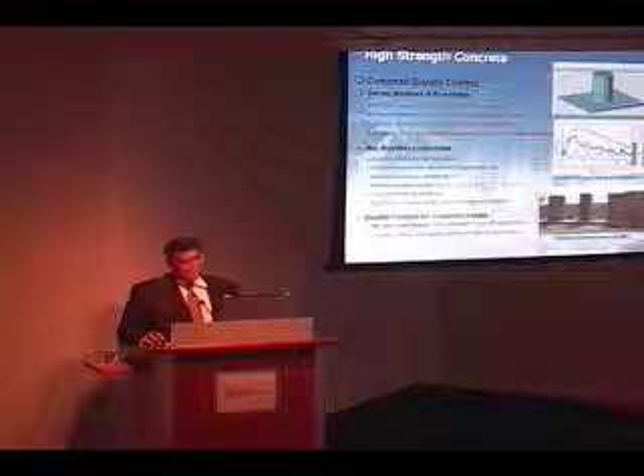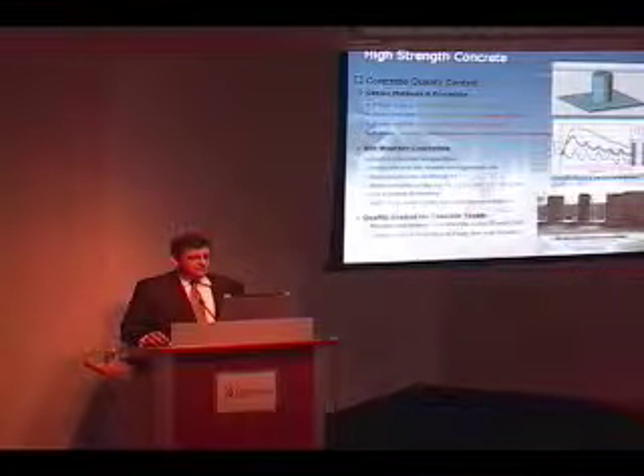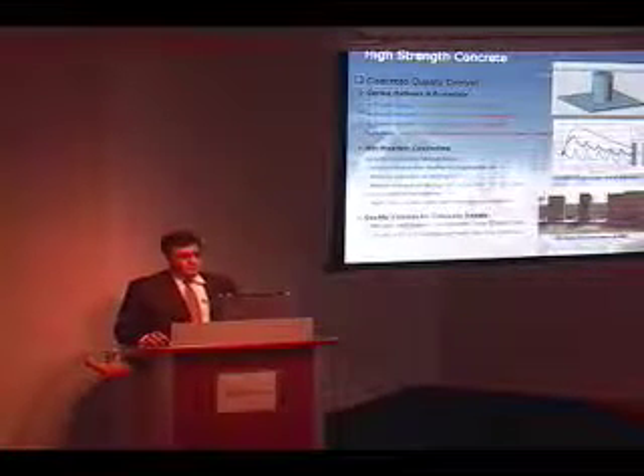Investigated the curing compounds for horizontal members such as the slab and the beams. And also for the podium, we used the curing compound and water ponding as much as possible, especially in the parking garage. Hot weather concreting, we needed to do special plans, such as to control the concrete temperature, chiller plant, ice shelters, and aggregate. Normal concrete mixing at about 31 degrees, mass concrete mixing at 28 degrees for any members that are less than 1.5 meter. For members that are exceeding 1.5 meter, we had to limit the temperature at 25 degrees centigrade.